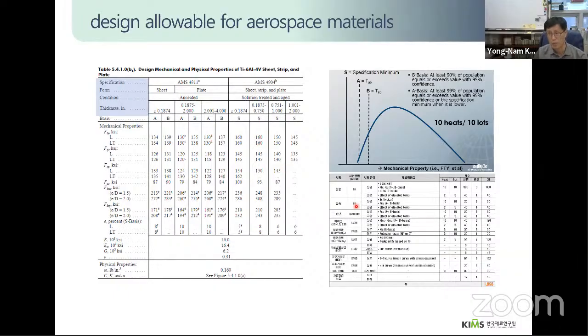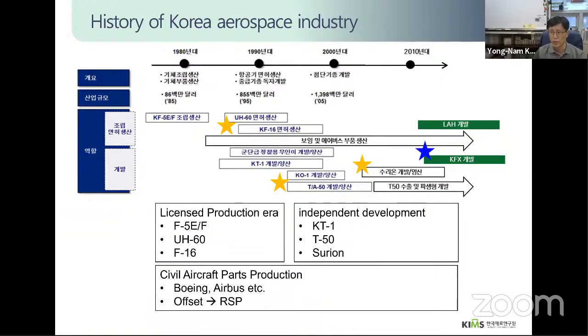alloys in the MMPDS handbook, which must be used from the design stage to obtain airworthiness certifications. To obtain design allowables for one material, a test matrix, as shown below here, requires a variety of tests with almost 1,800 specimens. Static tests such as tensile and compression basically obtain statistically safe values by collecting specimens from 10 heats and 10 lots of material samples, which means melting and manufacturing 10 times to provide for testing. Even one material presents different material properties depending on material type, heat treatment condition, and thickness. It means it takes quite a lot of effort and money to make this single design variable table.